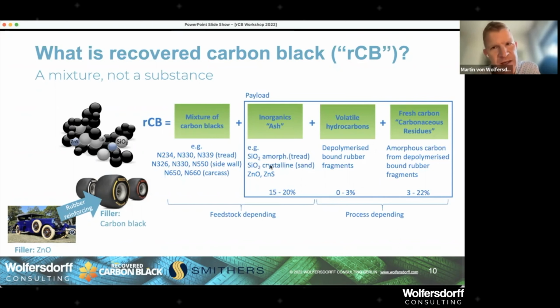What I would expect in the recovered carbon black is more the zinc sulfide, but there might have been high content of zinc oxide in the tire. Normally, the zinc oxide in the vulcanization reacts to zinc sulfide, but there might be zinc oxide in the process as well. And then we have two materials in the payload that depend on the process.